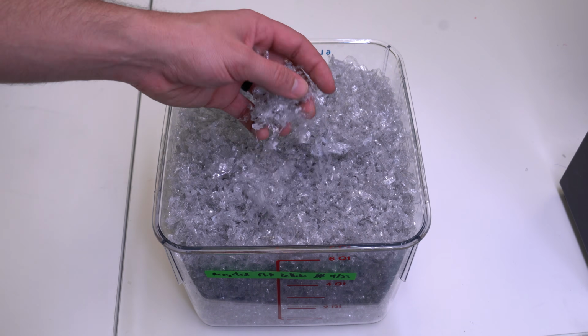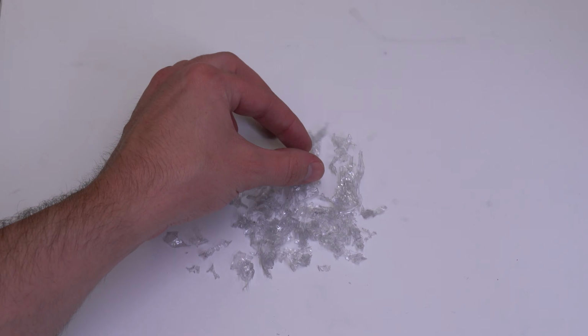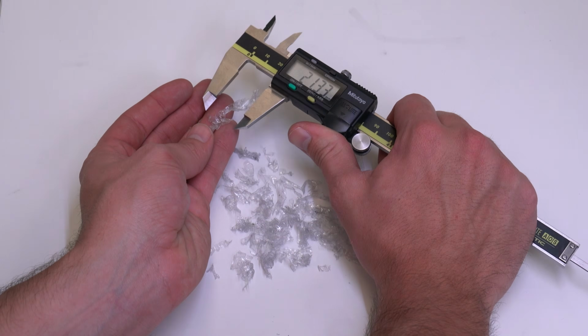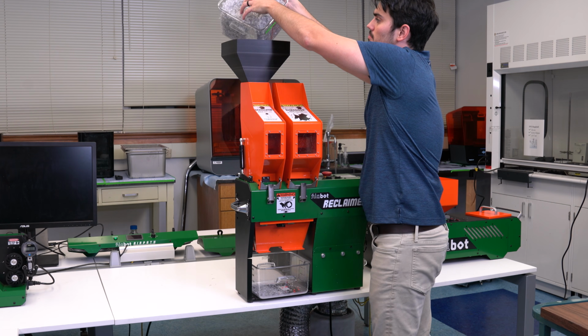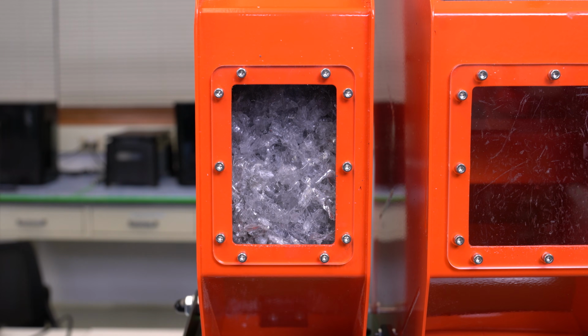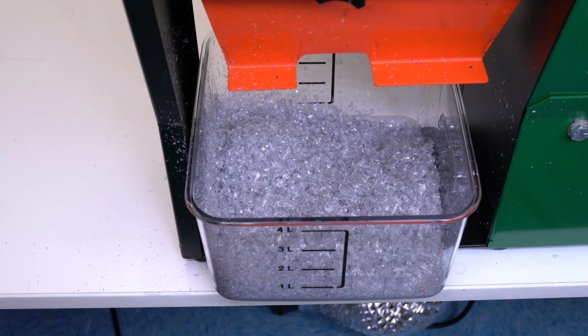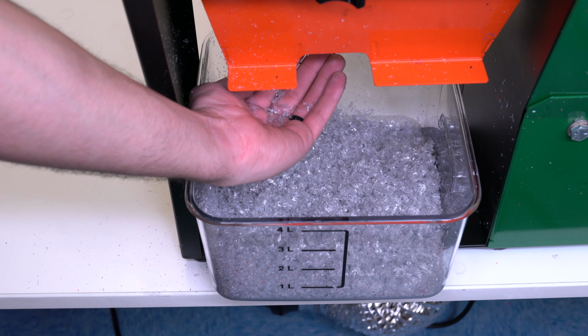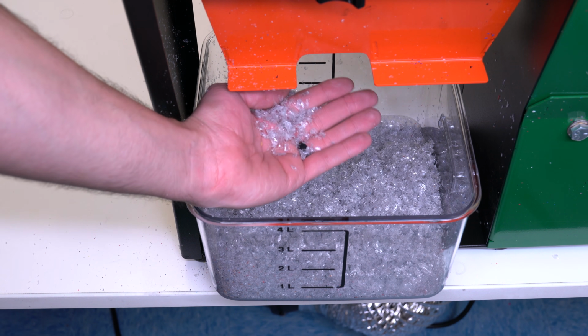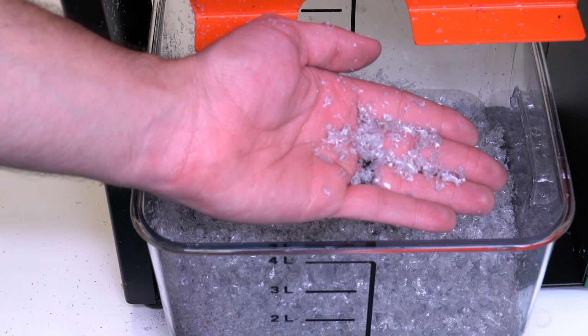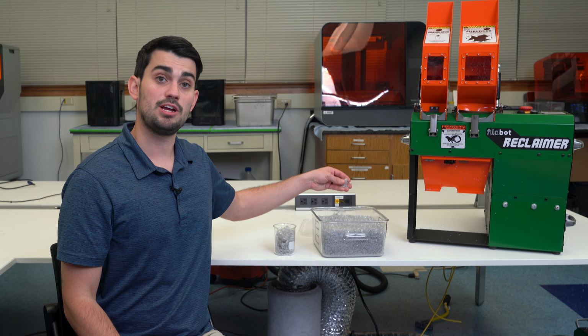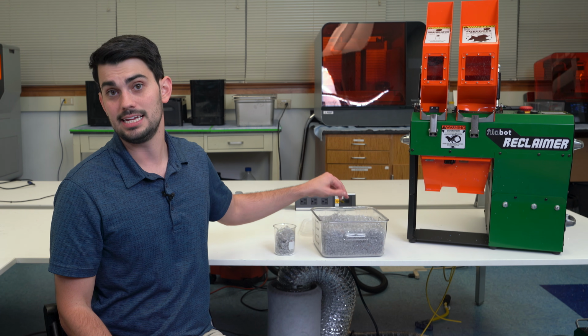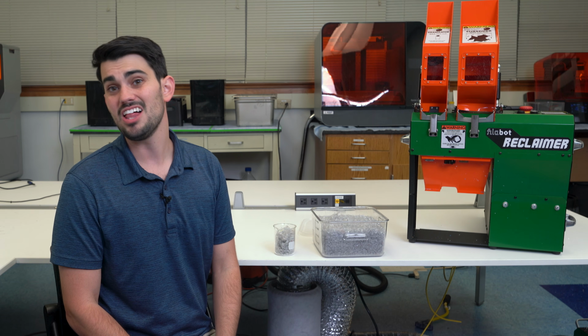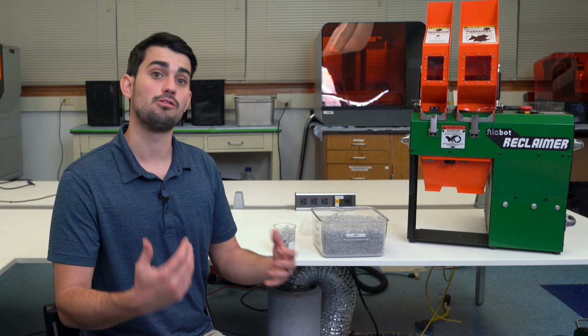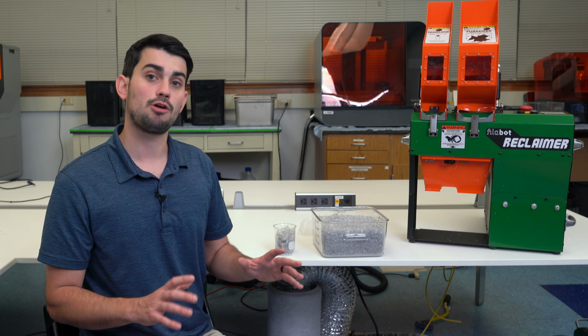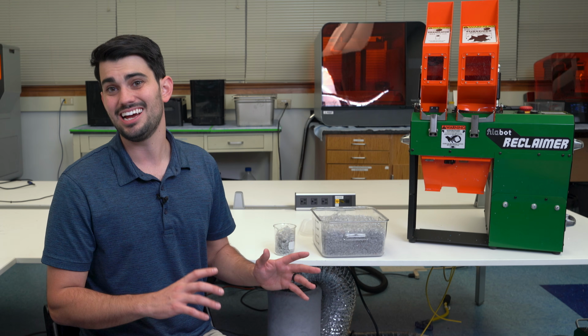The shredded material that comes out of Shreddy is not able to go right into the X6 extruder. It's too large. But fortunately, it is the right size for the granulator side of the reclaimer. After granulating the material a final time, we have a material that is small enough to fit between the flights of the X6 screw. But there is one more problem. The irregular shape of regrind can cause more than just a low bulk density. It can also affect the ability of the solids to follow gravity down the hopper and into the rotating flights of the screw. This property is aptly called the flowability of the solids.